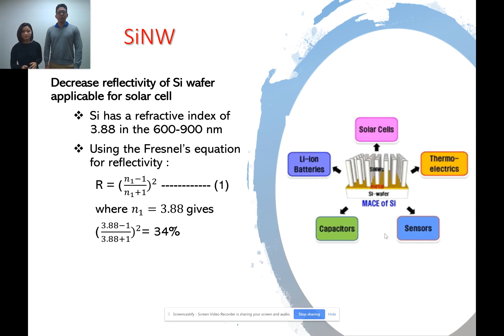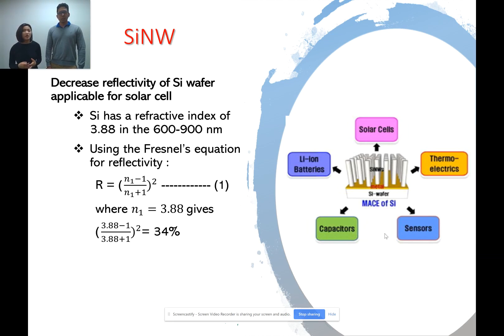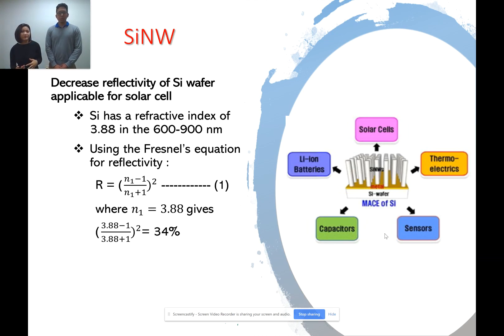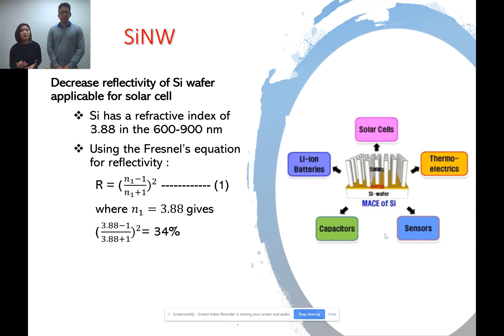Silicon nanowire is an integral part of nanotechnology. Silicon wafer's reflectivity can be explained using Fresnel equations, where N1, which is 3.88, is the index of refraction of silicon. Using this equation, we arrive at 34% reflectivity, meaning when photons hit the silicon wafers, 34% will reflect and only 66% will be absorbed. However, by growing silicon nanowires on a silicon substrate, we were able to reduce this 34% to approximately zero.